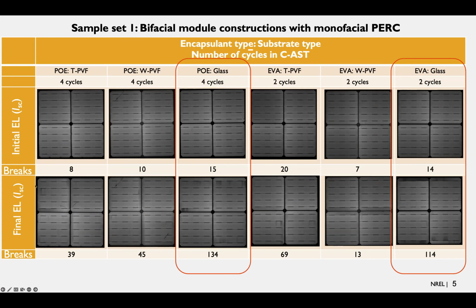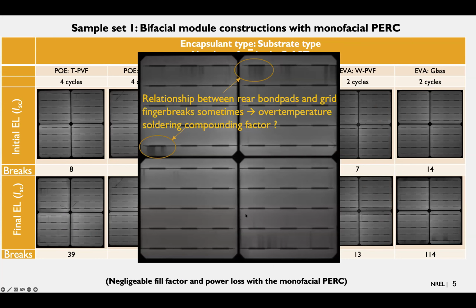And what we're looking at here is a quantification of the numbers of breaks that are observed at the beginning and at the end. And we can see, as highlighted in the red circles here, again, the ones with the glass substrate seem to lead to the most grid finger breaking. Here's a close-up, and what we're seeing is that it's not 100%, but there's some relationship between the rear bond pads and the grid finger breaks.